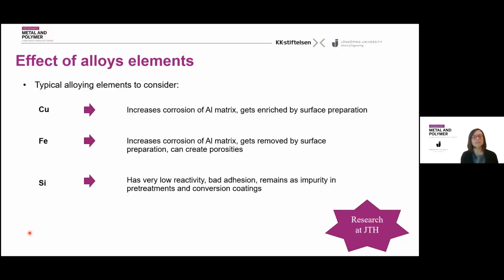Silicon is an element that is very common, of course, in cast aluminum components. It has a very low reactivity because it's not a metal. Having such low reactivity, it provides bad adhesion and increases the potential to create adhesion problems. Being so non-reactive, it remains there on the surface, not really interacting with anything, and is a sort of impurity that can remain embedded in your coatings or in your pre-treatment conversion coating.